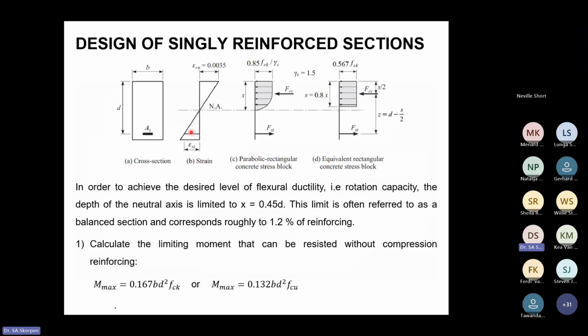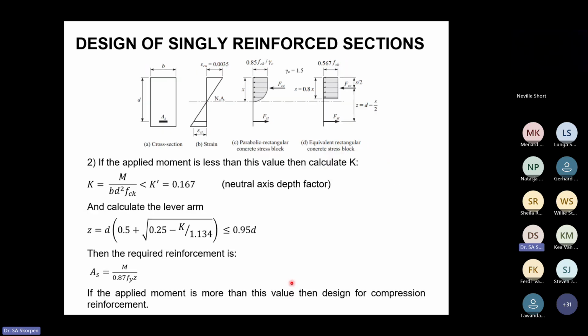So then when we're looking at the design of a reinforced section, and this is now what we call a singly reinforced cross section, we've just got tension reinforcement at the bottom here. To make sure that we've got enough ductility, we limit the depth of the stress block to 0.45 times the effective depth, d. This typically corresponds with a steel percentage of around 1.2%. We would start by checking what the limiting moment is without any compression reinforcement. And these are the two equations that you would use if you're using cylinder strength and cube strength.